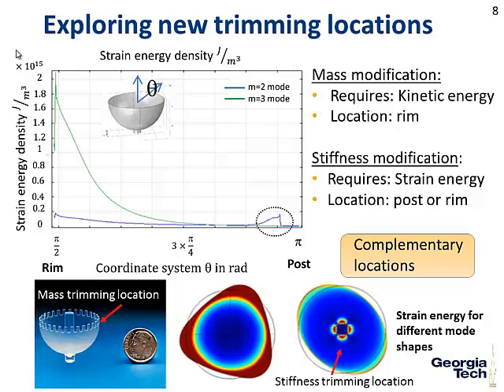So if, for example, you look at different modes, M=2, M=3, M=4, and so on, that Cornell just described, you can see that M=2 has a strain energy peak at the post that you can see in color here, whereas M=3 had almost none. If you really zoom in, you'll actually see a little peak, and they have the strain energy higher. So with our trimming technique, we can do mass modification at the rim, and we can also do stiffness modification at the bottom, and hence we have a larger trimming range than what people had before.